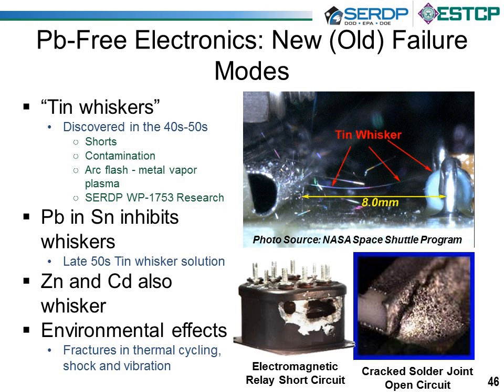We have zinc and cadmium, two other popular materials in electronic systems. Cadmium not so much because it has its own toxicity troubles, but with zinc we're seeing increased usage for corrosion protection on metal frame structures and electronic structures. And you want to be very careful of that. Zinc whiskers in floor tiles at computer centers have been very detrimental to electronics. There are environmental effects that Peter alluded to that challenge us in terms of fracturing the interconnects, particularly during harsher thermal cycling, shock and vibration.